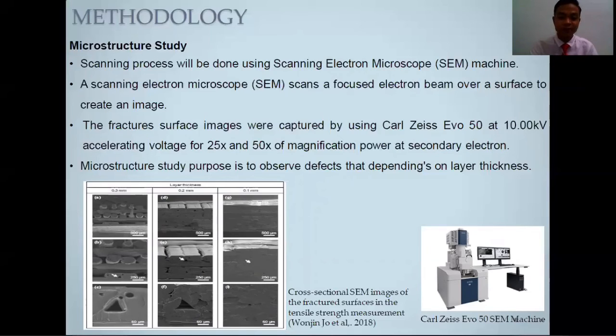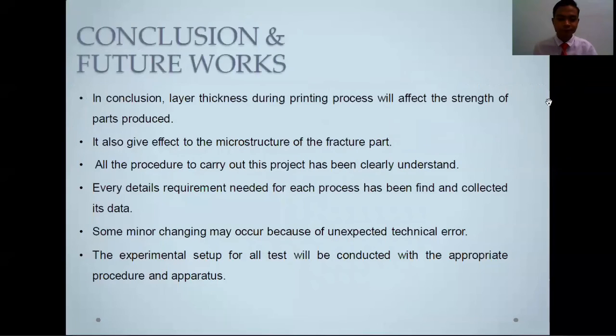As you can see in the figure below is an example of a cross-sectional SEM image of the fracture surface in the tensile strength measurement. In conclusion, layer thickness during the printing process will give an effect to the strength of the part produced. It also gives an effect to the microstructure of the fracture part.